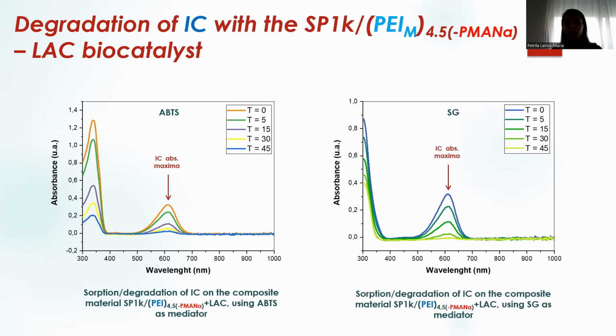The use of the second biocatalyst obtained by the immobilization of laccase on the composite material fabricated with polysodium methacrylate was assessed in similar conditions, observing that in the presence of both ABTS or syringaldehyde, the degradation efficiency reached 100% after 45 minutes.